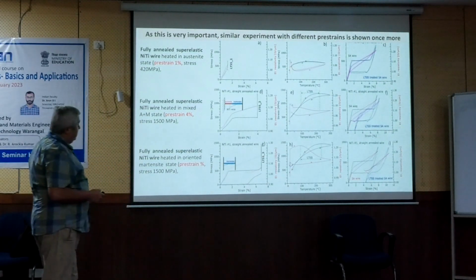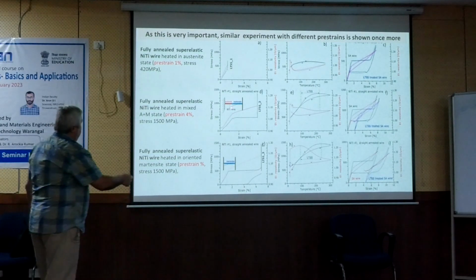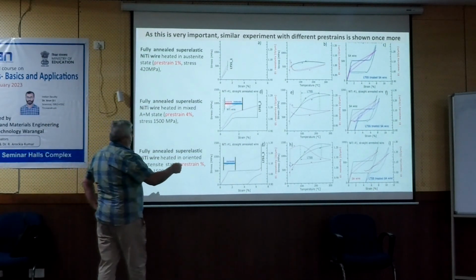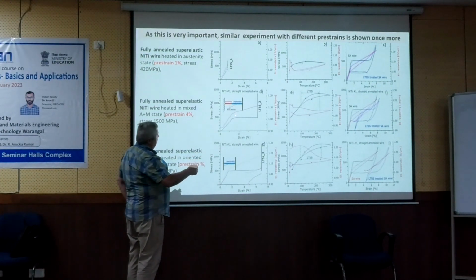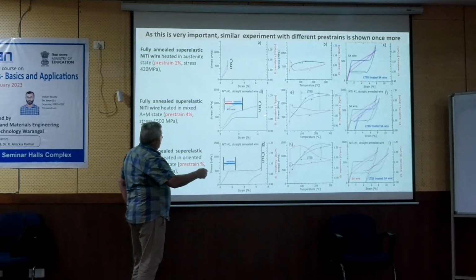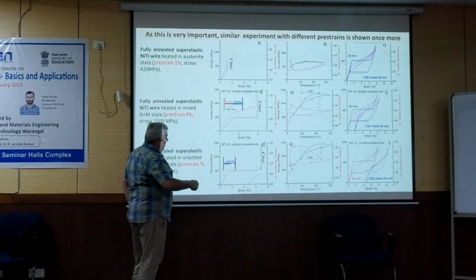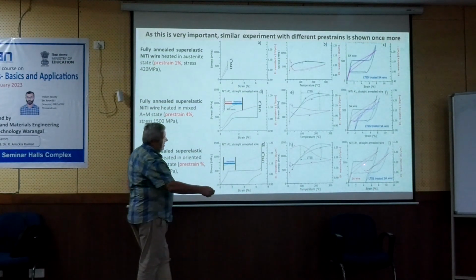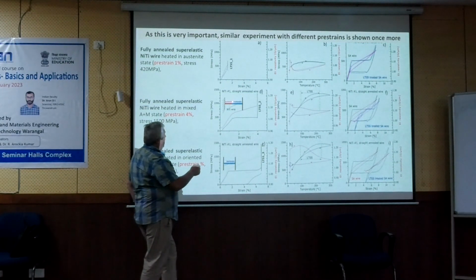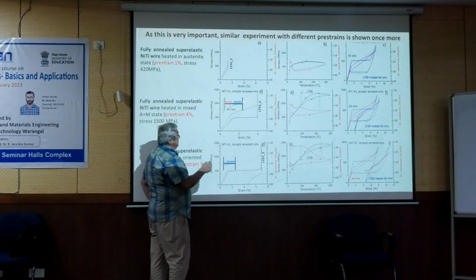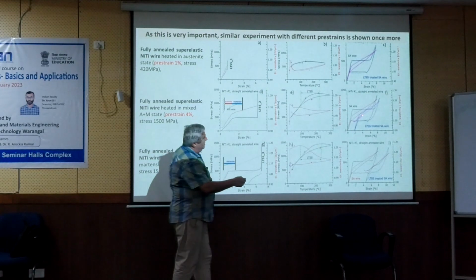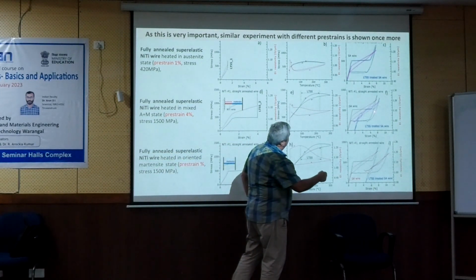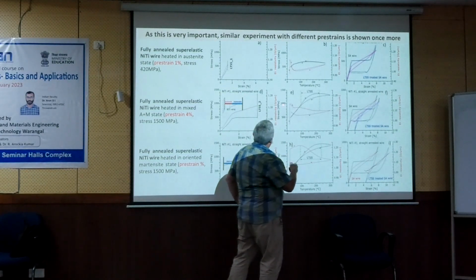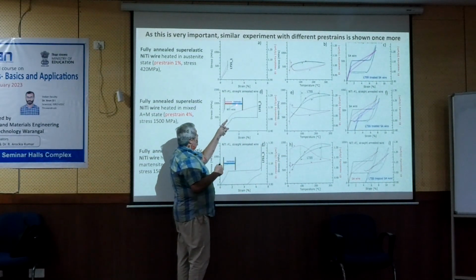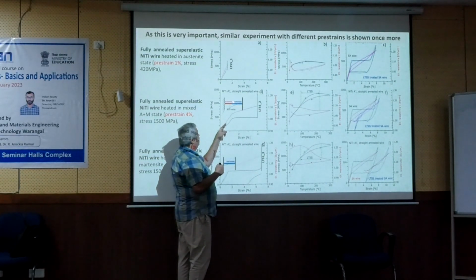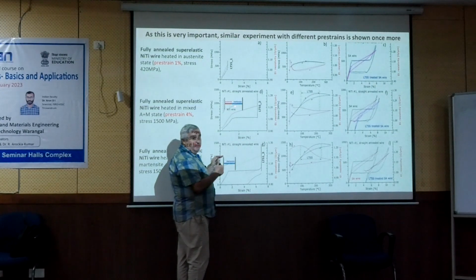Yeah. It is even so that if I take the wire, because it's localized, I can stretch it only to 4%. If I stretch it to 7%, it will be completely martensitic like this. If it's completely martensitic, I get such kind of perfect shape setting. But now I strain it only to 4%. Then you heat it, and you get such kind of hybrid, because only the part which is in martensite will be shape set. So this part will not be affected. This part will be affected.